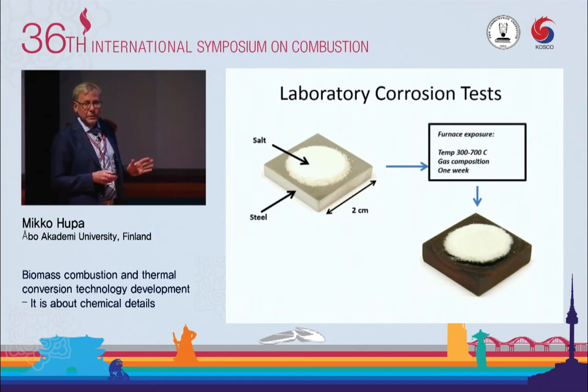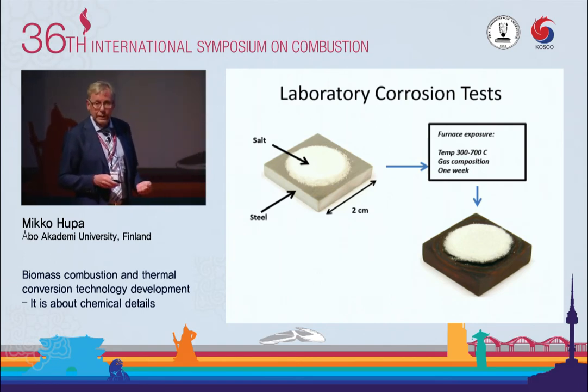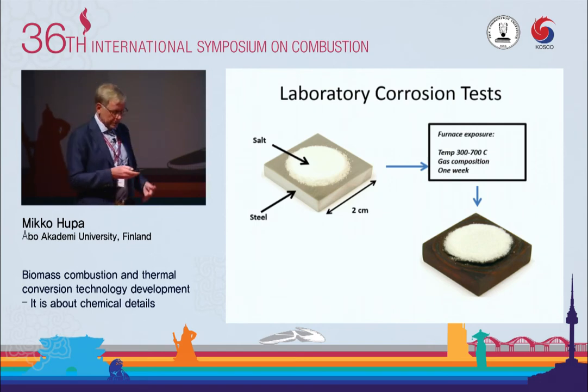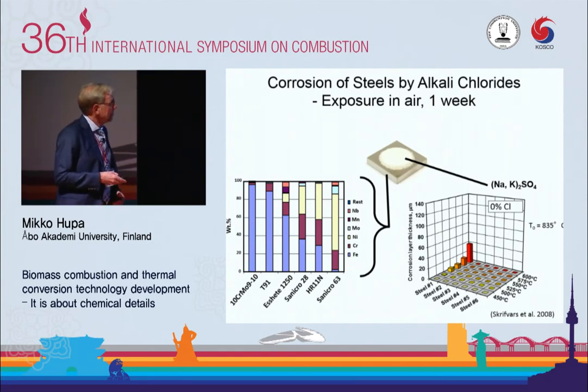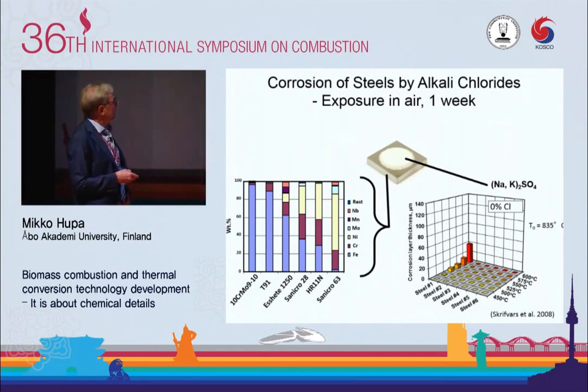In our laboratories, when we do corrosion, we do it quite simply. We have a sample plate of different steels, we put some salt on top of them, and treat them in a furnace-controlled atmosphere. One week has shown to be a long enough time to get a good signal. And then we cut the piece and do microscopy on that. Here I show one quite big study we did a while ago where we compared 6 different steels for chloride-induced corrosion. 6 steels, starting with carbon steel, with most of it iron, and then going, they are commercial steels, but systematically going to more and more advanced.